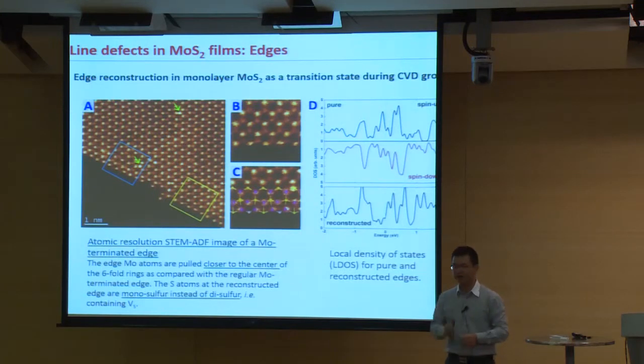We also look at the edges of this molybdenum sulfide, but unfortunately, this edge is not that stable under the microscopy, so we get just a few images. But anyway, from this image, you can see the configuration, the reconstruction of the sulfur and the moly atoms along the edges. So it's not that stable.